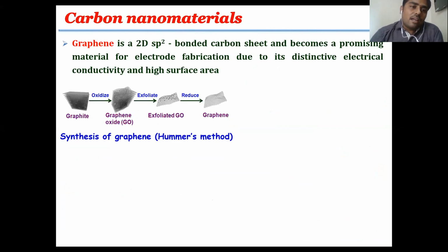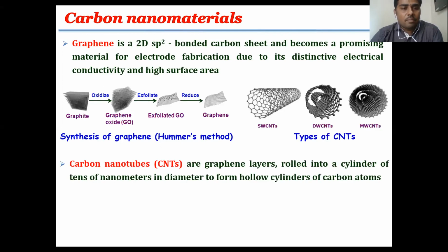Since the metal nanoparticles are costly, we go with low cost electrocatalysts such as carbon nanomaterials. Graphene is one of the carbon family. Graphene is a 2D sp2 hybridized sheet and becomes a promising material for electrode fabrication due to its distinctive electrical conductivity and high surface area. Generally, graphene is synthesized from graphene oxide, which is synthesized from graphite by the Hummers method. Nowadays we are using the modified Hummers method for the oxidation of graphite to graphene oxide, exfoliation of graphene oxide to exfoliated GO, and reduction of GO to reduced graphene oxide or graphene. CNTs are another type of carbon nanomaterial, graphene layers rolled into a cylinder of tens of nanometers in diameter to form hollow cylinders of carbon atoms.